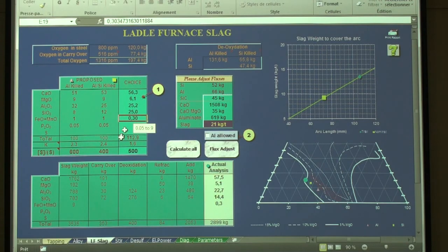So if I change, for example, I put here 25, of course I have to remove something, so the alumina will be penalized, so I will put 12 and MgO 7. Okay, it's a bit above 100, but the system will adjust it by itself. The K is the well-known basicity coefficient for the ladle. It's lime plus 2/3 of magnesia, divided by the alumina plus silica plus half of the other stuff.